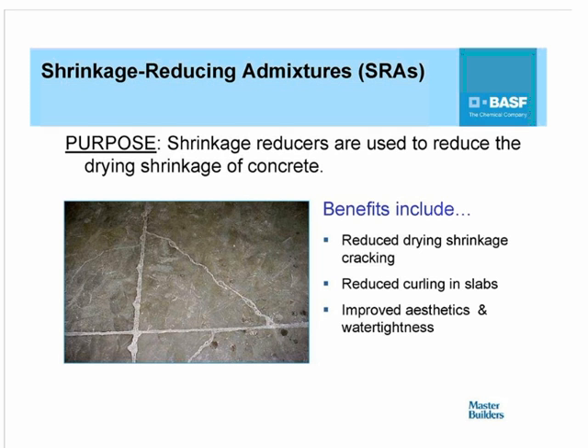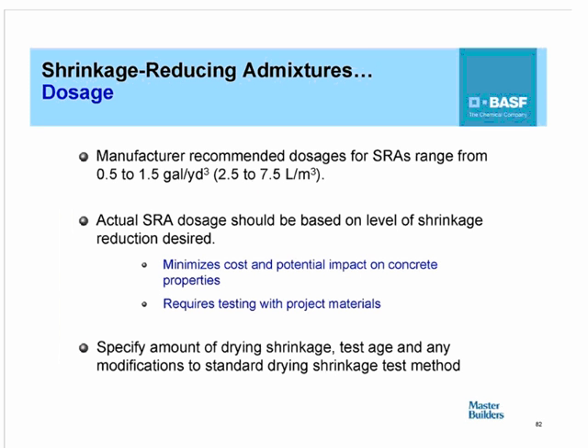Now, shrinkage-reducing admixtures are another group of admixtures that are increasingly being used in the marketplace. And the main purpose is to reduce the drying shrinkage of concrete, and by reducing the drying shrinkage of concrete, reduce the potential for drying shrinkage cracking and curling in slabs. In water-retaining structures, they also help in providing or improving the water tightness of the structures. These materials are typically used at dosages ranging from about half a gallon to 1.5 gallons per cubic yard, depending on how much shrinkage reduction is actually needed in the concrete.